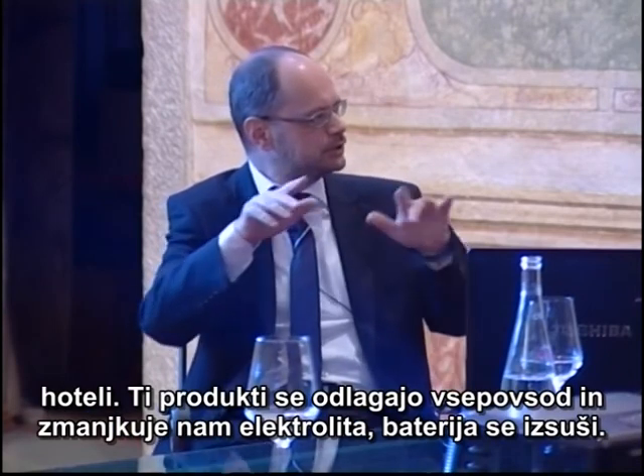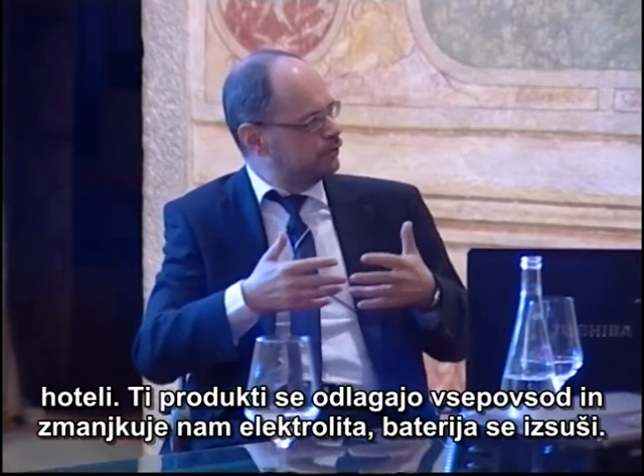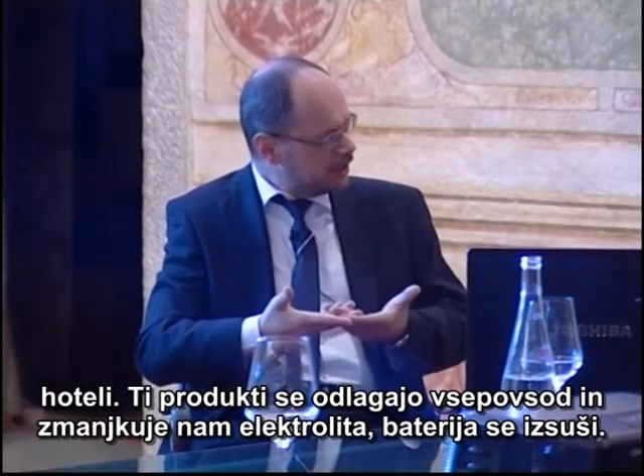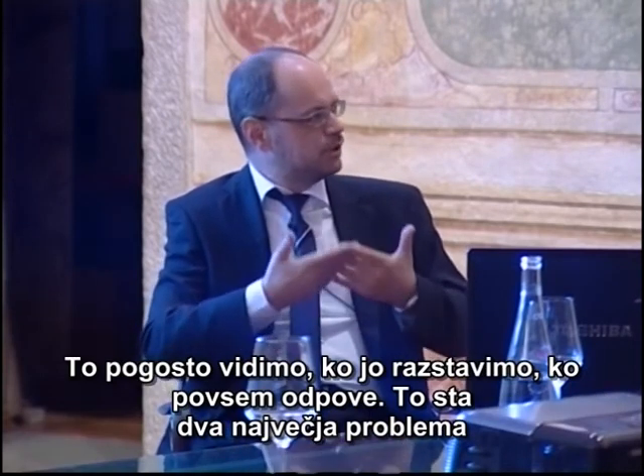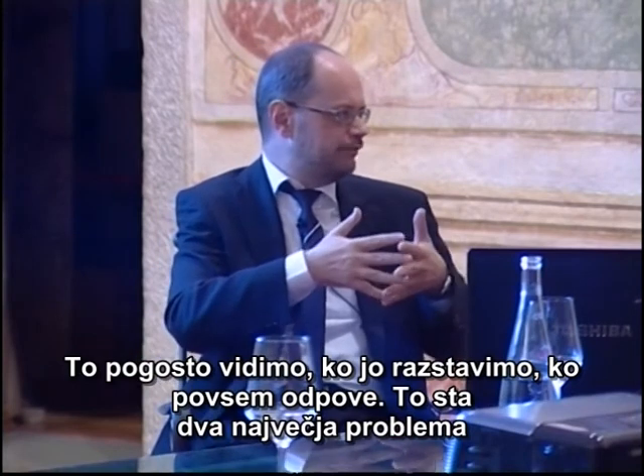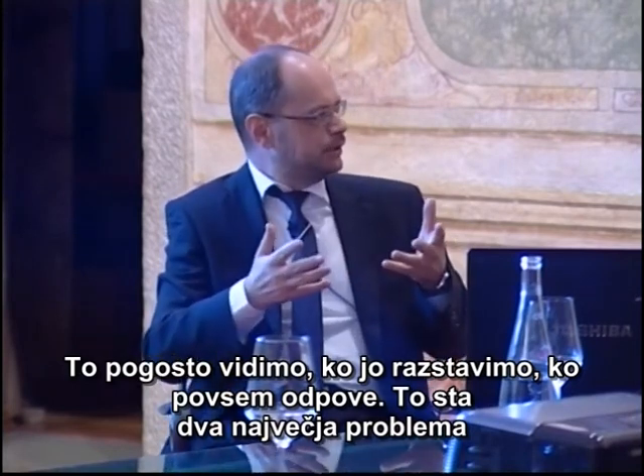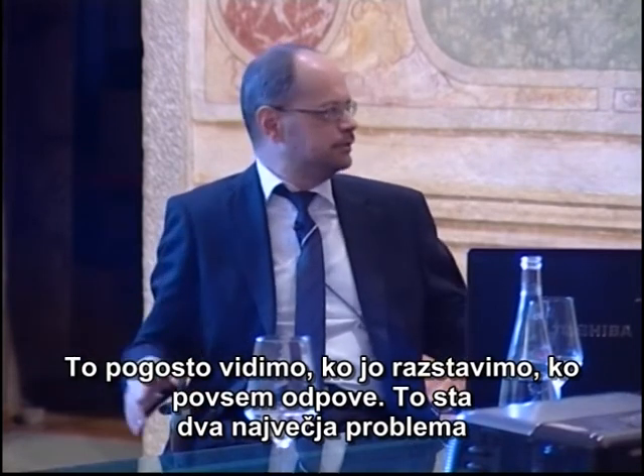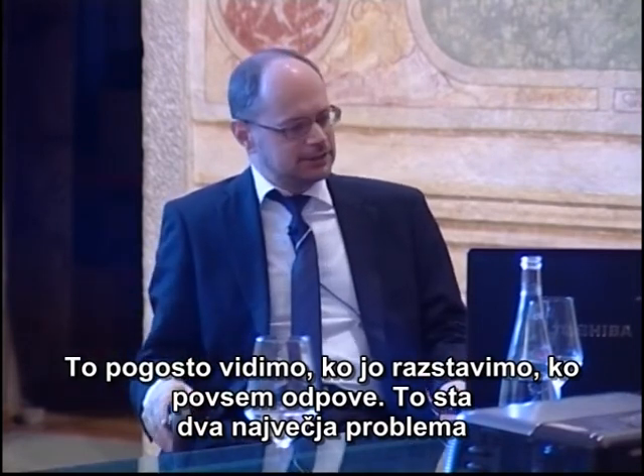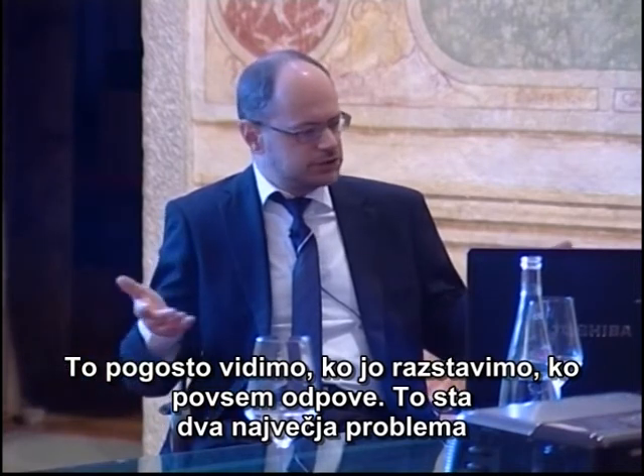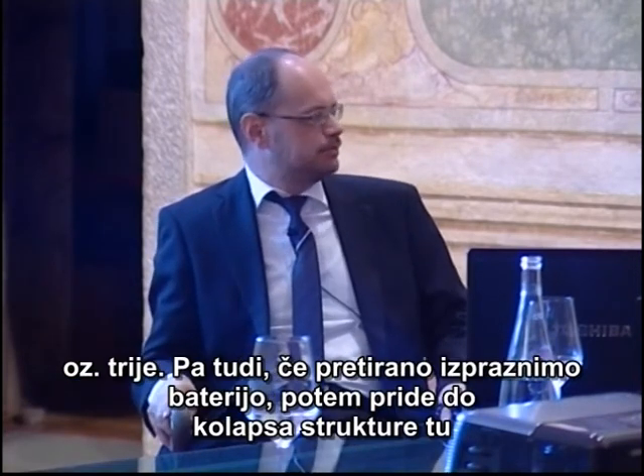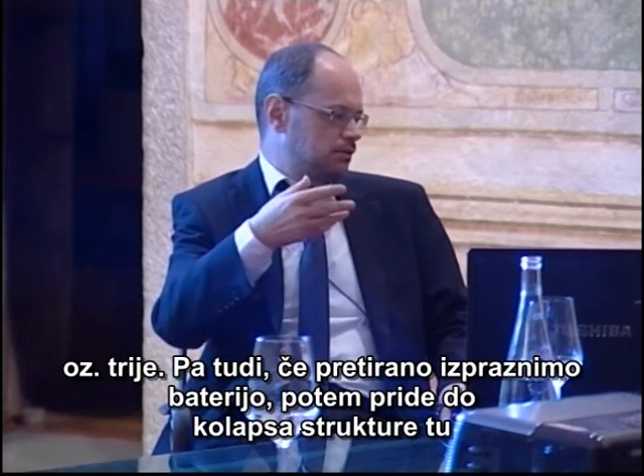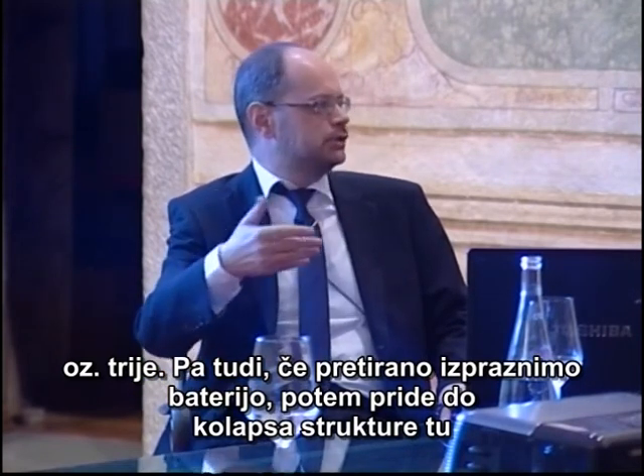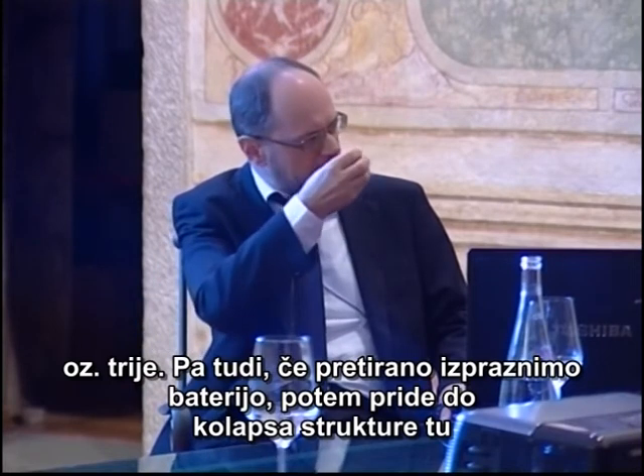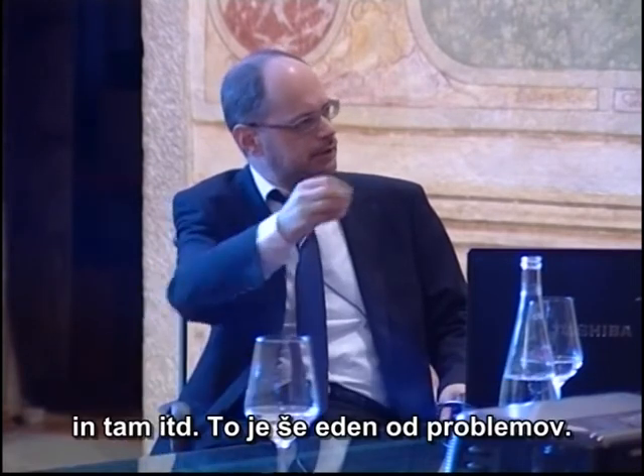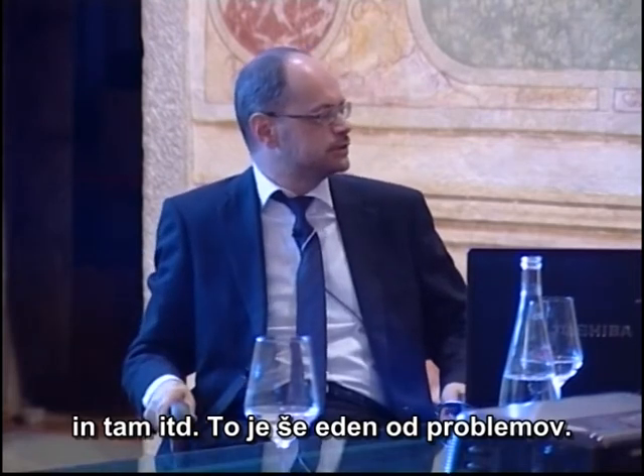And these products are deposited everywhere. You are running out of your electrolyte. Your material is drying up. This is very often seen when you disassemble a battery after it has died. So these two or three problems are the biggest problems. And of course, when you over-discharge, then you have an internal collapse of the structure here and there. This is also one of the reasons.